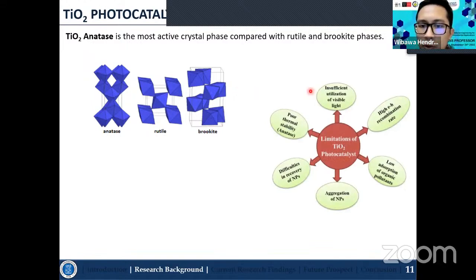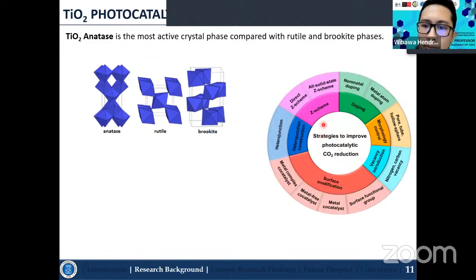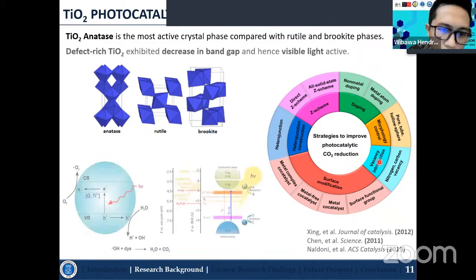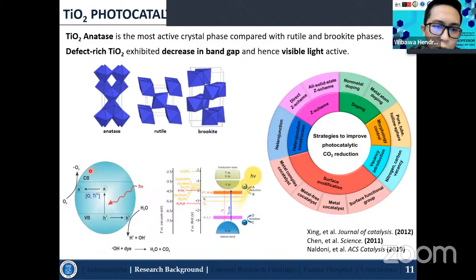However, the TiO2 photocatalyst has limitations. It has insufficient utilization of visible light because it can only be activated by UV light. It has a high electron and hole recombination rate, because the lifetime of the electron in the conduction band is very short. It also tends to form aggregations of nanoparticles and has low adsorption of organic pollutants. Therefore, to improve photocatalytic activity for wastewater treatment or CO2 reduction, there are several approaches that can be used, such as doping, surface modification, heterojunction construction, or vacancy introduction and defect generation.